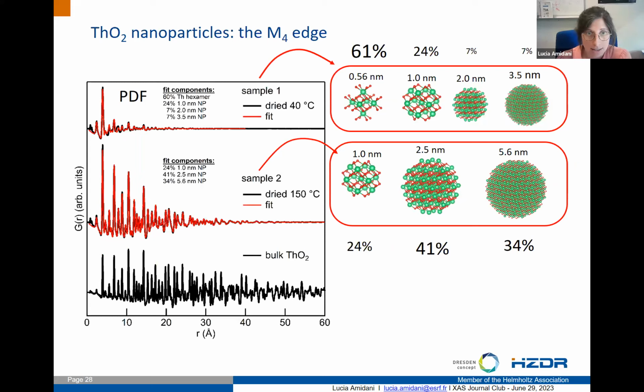And what are they saying? The most important information we got from here is that, while from diffraction I knew them to be 2.5 nanometer nanoparticles, indeed we find it's a distribution, and the dominant contribution comes from something that is 0.56 nanometers, the smallest unit I can cut.